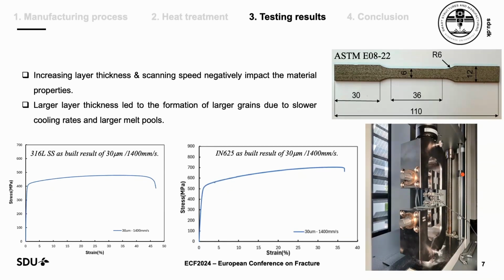As I said previously, we changed other process parameters such as layer thickness, scanning speed, and so on. In those studies for as-built samples, we saw that increasing layer thickness or scanning speed negatively impacts the material property. The main reason, as the previous talk mentioned, is the energy density. Energy density has laser power as the numerator, and layer thickness, scanning speed, and hatch spacing in the denominator. So if we increase the layer thickness, scanning speed, or hatch spacing, we are decreasing energy density.